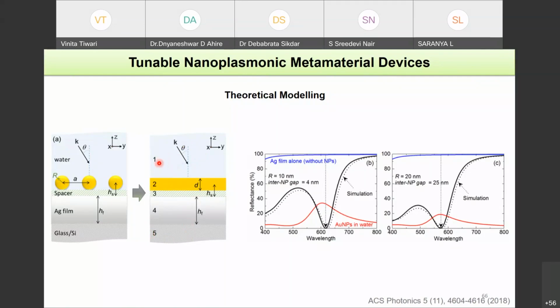And what you will do, you will have how many interfaces you have? You have interface 1, 2, then you have interface 2, 3, you have interface 3, 4, you have interface 4, 5. How many layers you have? Layer 2, layer 3, layer 4, right? And now when you put all these matrices in the proper order and simply multiply them, from the overall matrix, you can obtain what is reflection coefficient, what is transmission coefficient, and you can plot it. So this is what we have shown here.